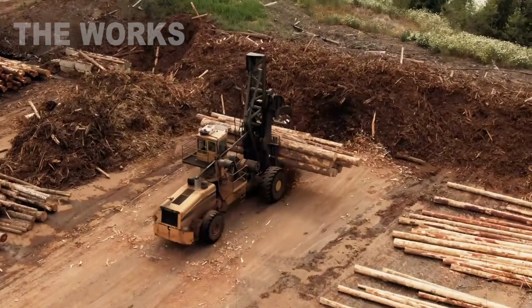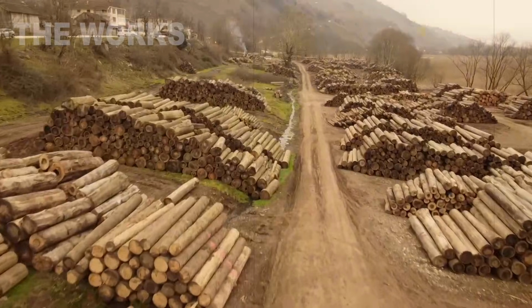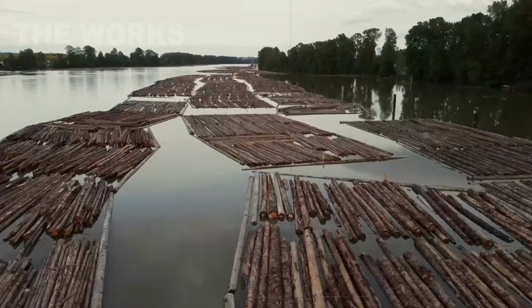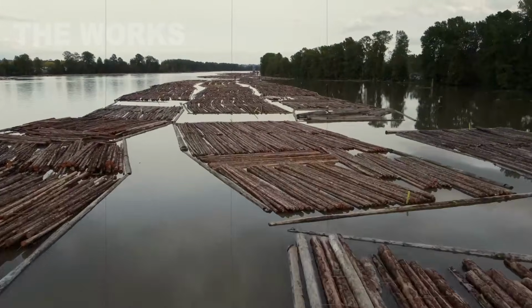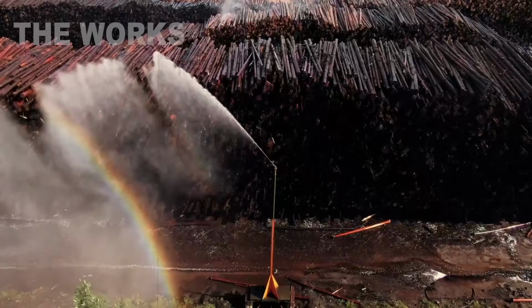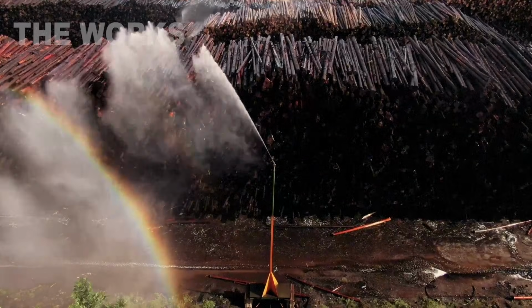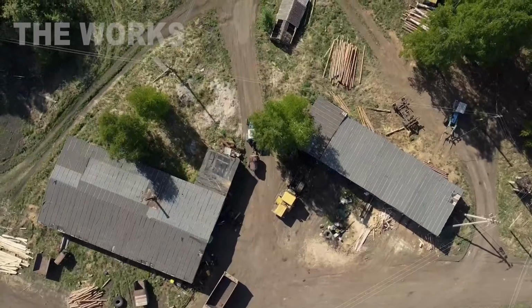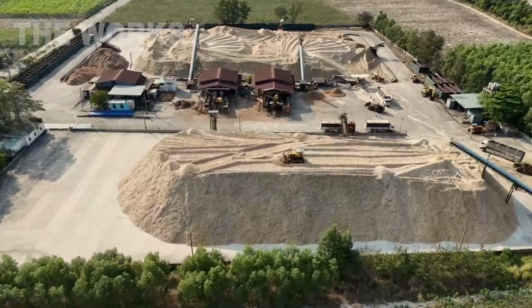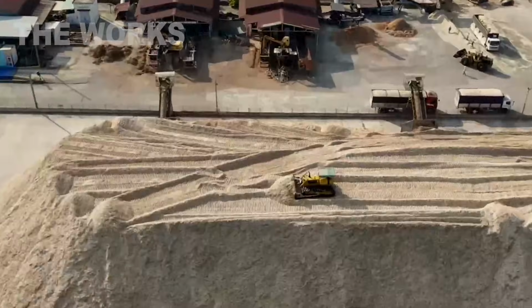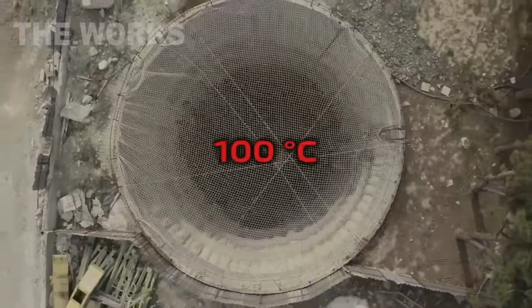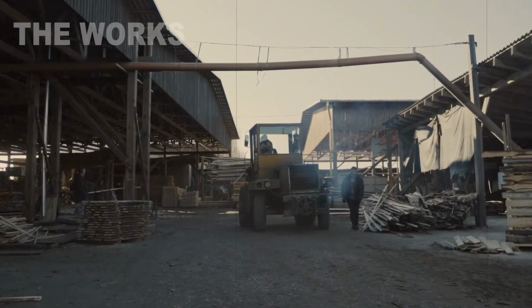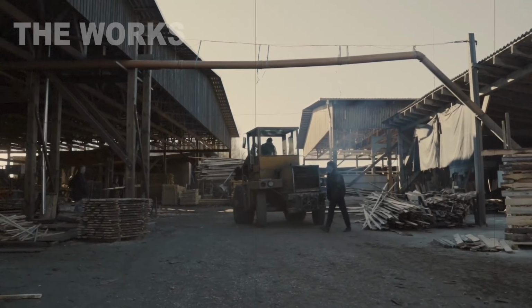The logs are submerged in enormous pools of hot water or placed in special chambers filled with hot steam. This isn't about cleanliness. This process, lasting anywhere from several hours to several days, at temperatures around 212 degrees Fahrenheit, does two crucial things. It softens the wood, making it more pliable and cooperative for cutting, and it transforms its color, making it richer and more uniform.